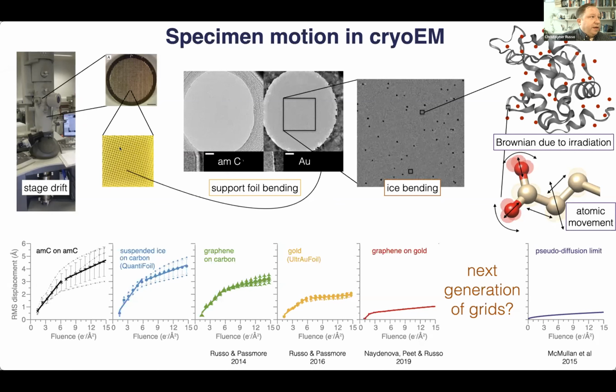And then about 10 years ago now, almost, we realized that actually there was another form of specimen movement that was caused by the differential contraction of the foil, which was suspended across the normal cryo-EM grid that we would use. So you had a metal grid and you had a carbon foil suspended across it, and the differential contraction of those two during preparation caused it to crinkle up and led to instability in the specimen. And so by making the grid and the foil out of one material, in this case gold, you eliminated this form of differential contraction and eliminated the movement that was caused by it. And that was basically what's being summarized here.